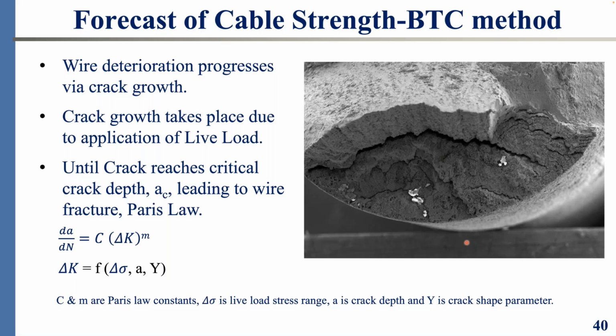What you see here is the Paris law. That calculates the incremental increase in the crack growth per n, which is the number of cycles. That is, of course, correlated with the live loads, and that is a function of delta K, which is in turn a function of the stress, the live load stress range, and the crack depth, and Y is the crack shape geometry factor that I talked about a couple of slides ago. And we are able to determine the life of that wire to a very high level of accuracy, and the high level of confidence. Take that as a springboard to forecast the cable life.